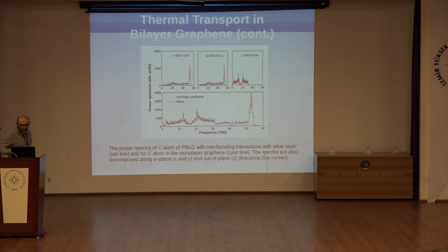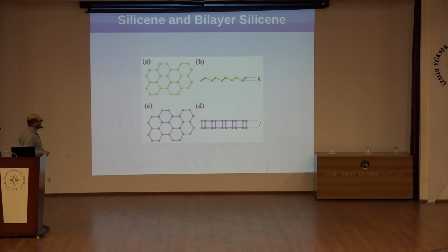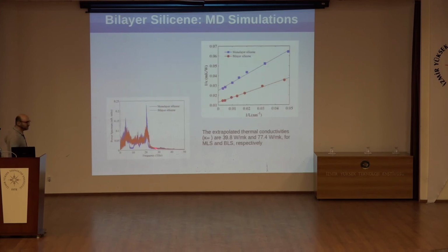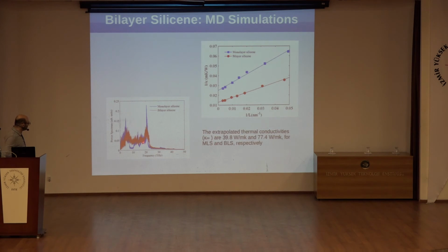The other case that we studied was the comparison between bilayer and single layer graphene. The other system that we have studied was silicene. Silicene has some sort of ripple, a very small amount of out-of-plane displacement, and by creating a bilayer silicene, it is possible to change the vibrational density of states of phonons. As you see, there is a gap in the density of states of phonons for pure silicene, but by creating these bonds, this disappears, and the thermal conductivity increased by almost a factor of 2.